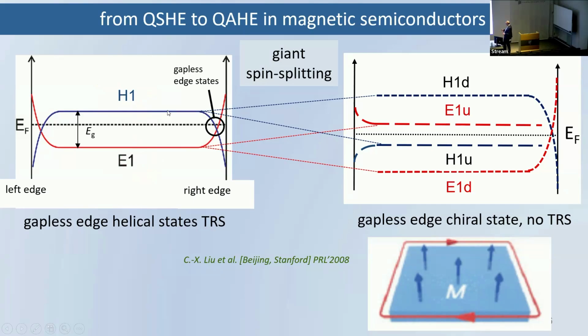So if you cleverly do that, if you put appropriate impurities and an appropriate number of these impurities, you end up with a very interesting situation, that you have an inverted situation in one spin channel, but not an inverted situation in the other spin channel. So you have boundary states, which now can only carry one spin direction, because the topological situation occurs for only one spin channel. And you expect, therefore, chiral states, not helical states. Time reversal symmetry is broken by the presence of non-zero magnetization, and Kramers theorem is not present. You should expect something like that.